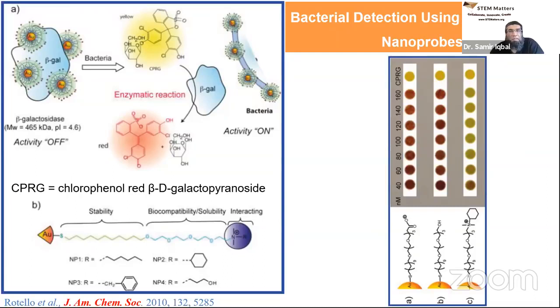And the continuation of the same question, do these bonds get maintained or perturbed during processing? Well, it really depends on how you stabilize your particles. If they are simply stabilized by electrostatic stabilization, then they are not very stable, and they would aggregate even if there is a minute amount of some electrolyte. But if they're covalently stabilized, which you really need for these kinds of bio applications, and I will talk about the stability of these particles in some later slide, then you need to covalently stabilize them with, for example, some peptides. If they are covalently functionalized with peptides, then they become highly stable, so they do not aggregate in the presence of electrolytes.